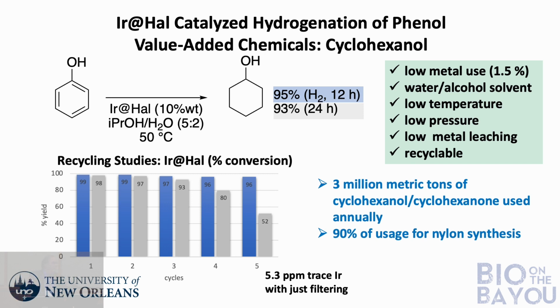Okay, so we've basically achieved all our goals here in the sense that we've reduced the waste stream, no organic solvents. We've reduced the energy component in the sense that we don't have to heat this too much. And essentially, we don't have to use dangerous high pressures of hydrogen gas. Okay. We can also do this same reaction with this catalyst without hydrogen at all, just using isopropanol as our source of hydrogen. And so it takes a little longer, but we still get really good conversion to essentially the cyclohexanol.